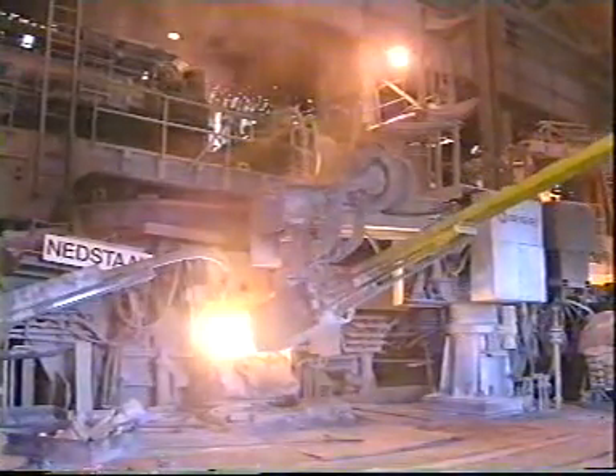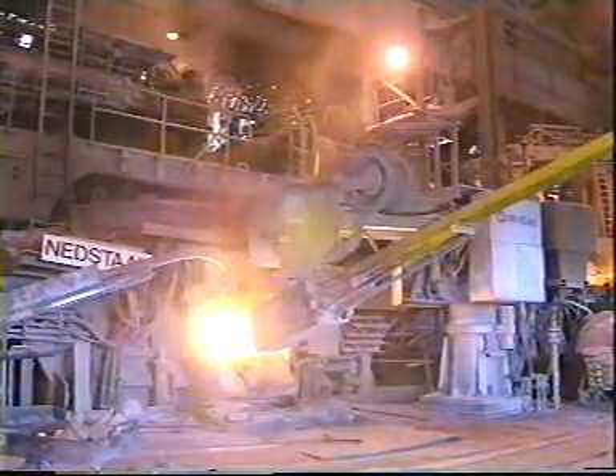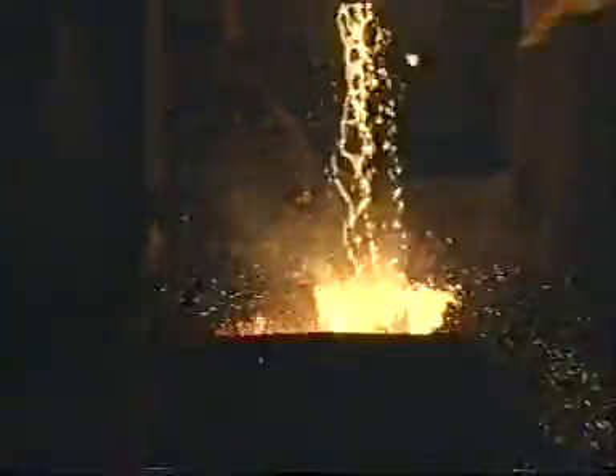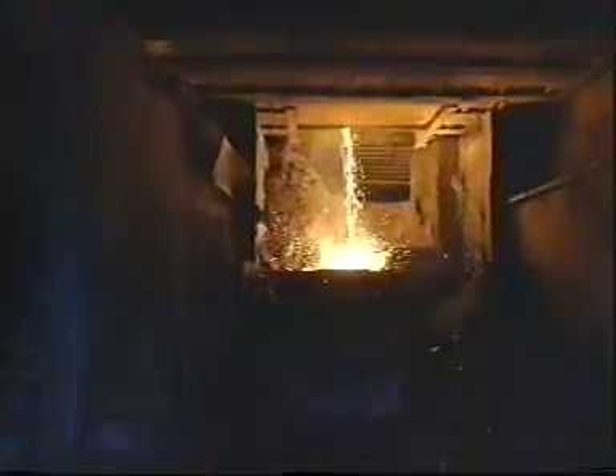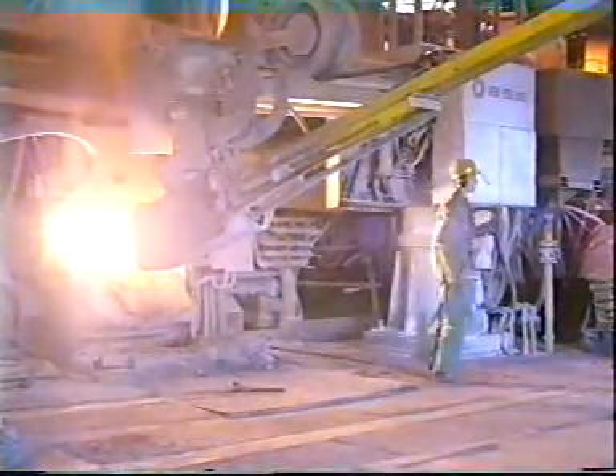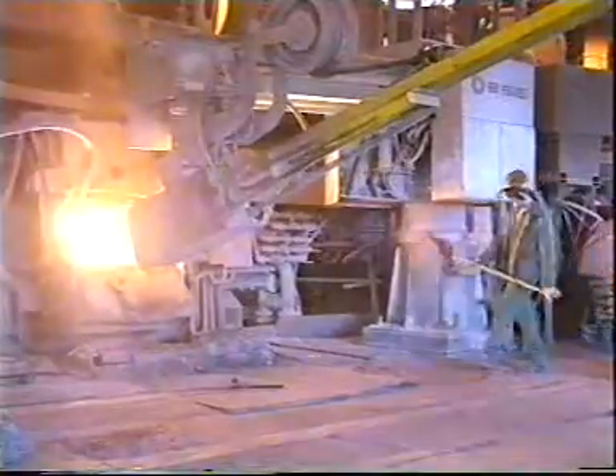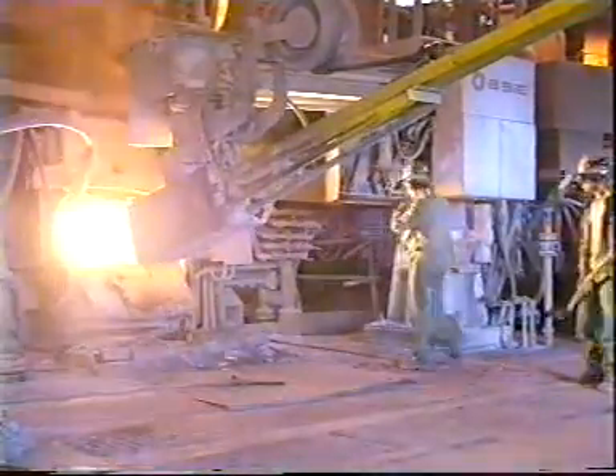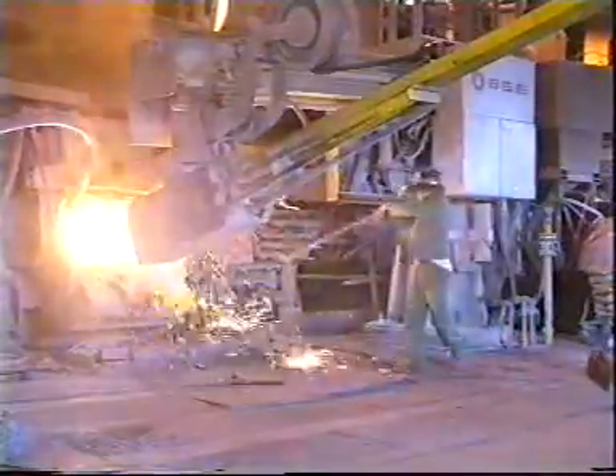Boiling, due to carbon oxidation, helps to remove harmful gases like nitrogen and hydrogen. Chemical reactions between bath and slag bind undesirable elements like phosphorus and silicon. The oxidizing slag is continuously renewed by tapping the slag and adding new lime. Fluorspar is added to improve the fluidity of the slag. The bath temperature is about 1650 degrees centigrade.